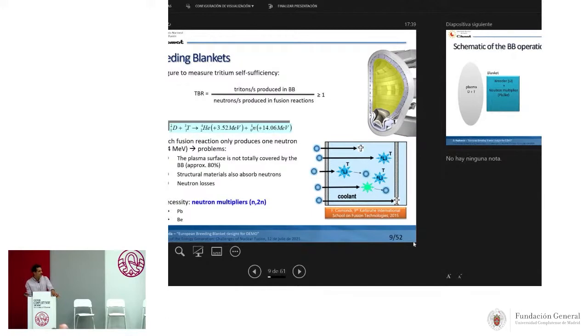I said that the deuterium-tritium reaction only produces one neutron, and this neutron has to directly impact the lithium blanket. Okay? And in this reaction, we only produce one tritium. So we have one neutron, one tritium. This means that if we lose some neutrons on the way, we never will reach the self-sufficiency of the reactor. This is quite important. And we are going to lose neutrons.